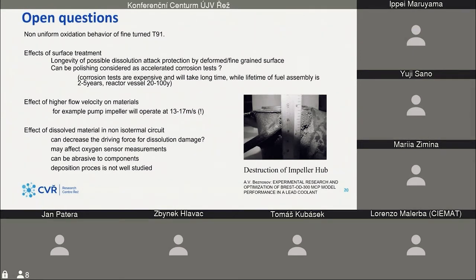Also, the effect of higher flow is unknown at this moment, because we calculated with Sigma company that the impeller pump will operate at something like 13 to 17 meters per second of relative speed between blades and the liquid lead. So the behavior of this material in this regime is completely unknown. Also, there are some questions connected to lost material in the circuit. It's because the oxide layers are peeling off and make it impure, and the question now is what happens there. If they affect the oxygen sensor measurements, for example, it will have an impact on safe operation, or they can be abrasive for components, and how this deposition process will happen is not very well studied, so these are still open questions.